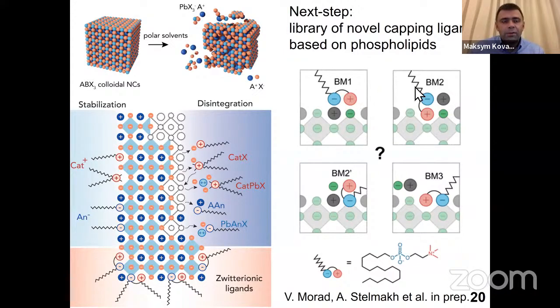Without going too much into detail, I will just tell you that we tested several possibilities, such as attachment of a ligand simply by adhering to the surface, or displacive attachment, which we initially assumed, where the phospholipid displaces a pair of ions and incorporates itself into the AX-terminated 100 facet. So our conclusions are that this binding mode 3 is much more likely than any other one depicted on the slide. But the most interesting finding was also to question whether this quaternary ammonium moiety, typical for phospholipids, is ideal or not.